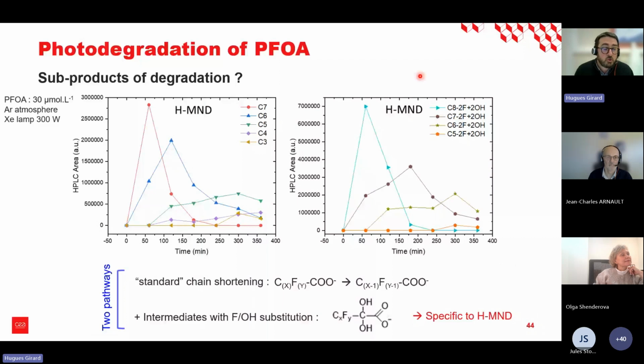So what about the subproducts? Because up to now, what I presented was the consumption of the PFOA, but then after you're going to have all the subproducts, which are also an issue. And what we observed, I will not go into all the details, is a quite standard chain shortening. So it means that we go from the C8 molecule to the C7, C6, and so on progressively in time. But also what is really specific to the milled nanodiamond, that we are not able to observe with the detonation one, is that we have another mechanism in which you will have a substitution of the fluorine by an OH group.